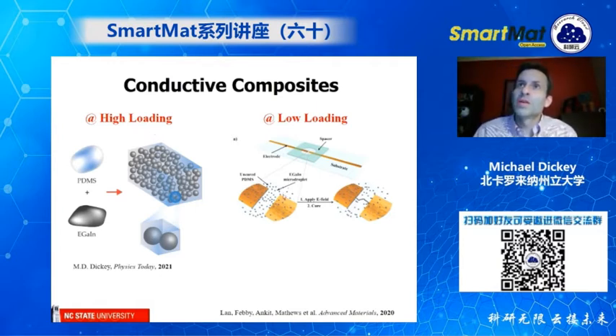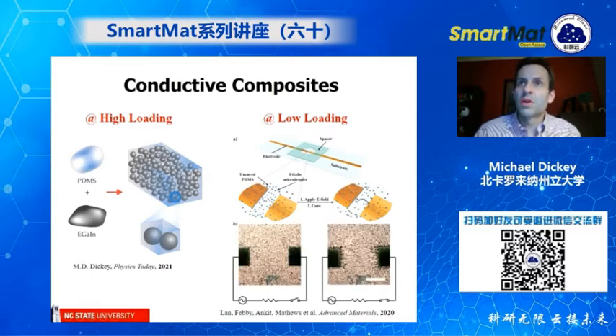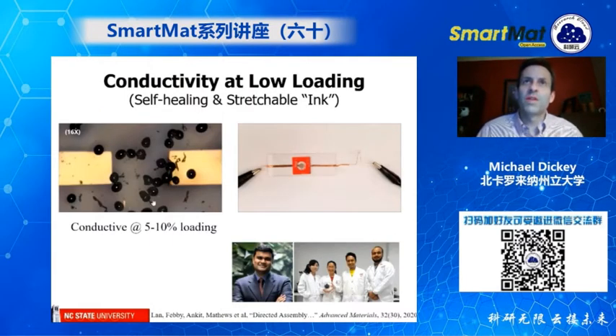And the way that we do it is by using what's called dielectrophoresis. We basically take electrodes and apply a voltage, which creates electric fields, which causes these particles to line up together and combine. So this is a picture of these liquid metal particles in liquid silicone, and we apply the voltage and you can see that they're lining up. So let me show you a video of this.